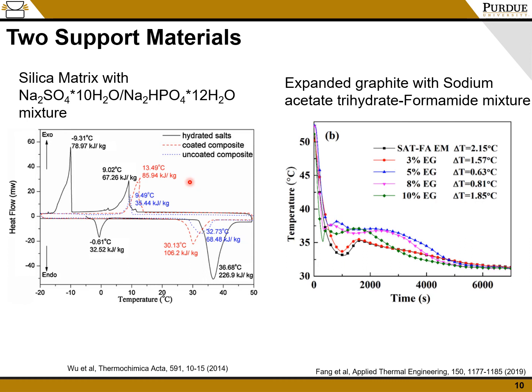Interestingly enough, the coated composite was better than the uncoated composite because the coating prevented water loss during those thermal cycles, as well as reduced interactions of the salt hydrates with the silica matrix that can affect the thermal capabilities of the salt hydrate. And expanded graphite being another support material of interest, they tested this with sodium acetate trihydrate and a formamide mixture. And you can see that the pure salt hydrate mixture experienced more supercooling than the mixture when it had a 5 weight % expanded graphite added into the composite. That greatly reduced this divot right here and had a more even phase transition with minimal supercooling, a very promising thing to see when adding expanded graphite. In addition, the thermal cycle was stable for the 10 cycles that this composite was tested for as well.